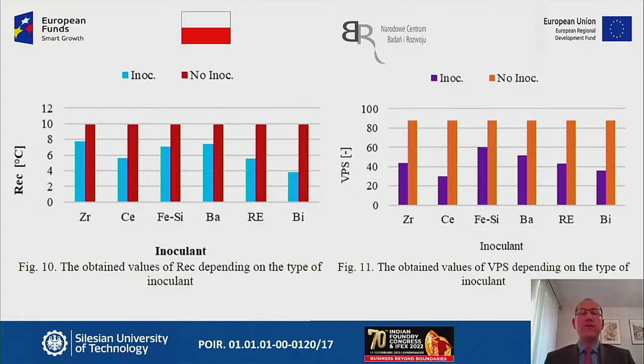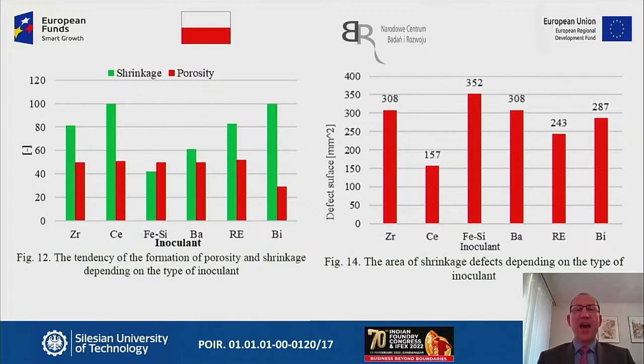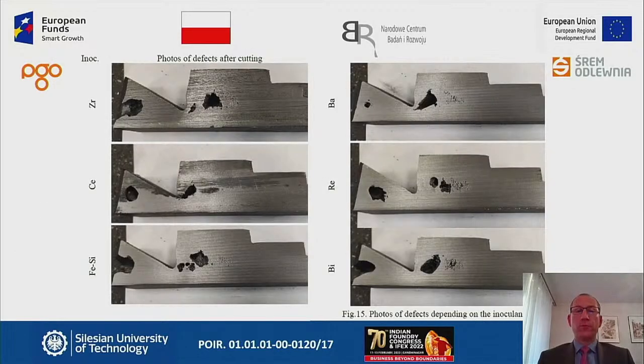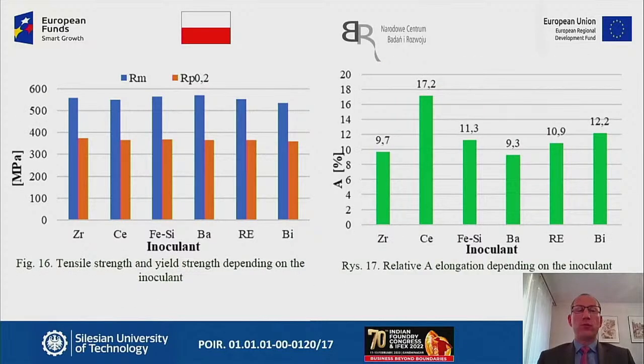And recalescence and VPS parameter, very important when you consider the shape and the shape factor of the nodular graphite precipitation and so on, and some other parameters like shrinkage and porosity, which are obviously very important from the quality of the castings point of view. We check the macro features of our sample castings, and here you can see the results of this for various inoculants, and the mechanicals for various inoculants, like on the left one is UTS, and on the right one is elongation. As I said, very nice results.